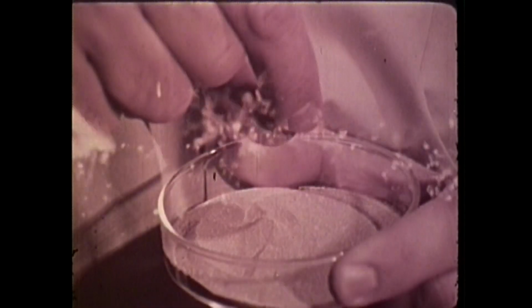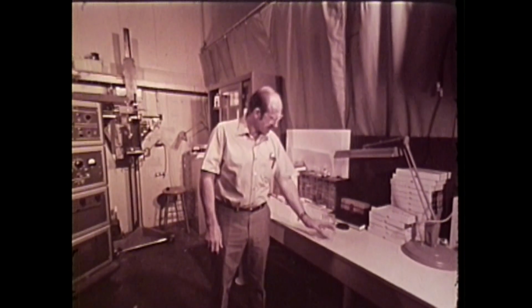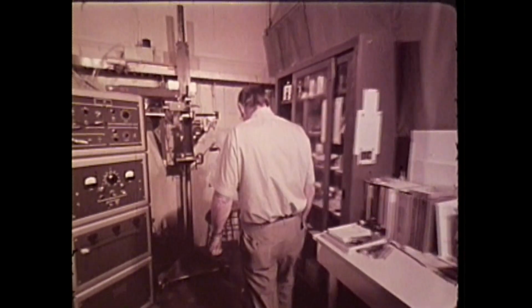The metal, however, tends to agglomerate during combustion and becomes coated with oxide, which inhibits complete burning. We were the first to determine the actual mechanism of particle agglomeration, and we're learning to reduce the process by pre-treating the aluminum before including it in the formulation. We're also studying the use of other metals in propellant formulations.